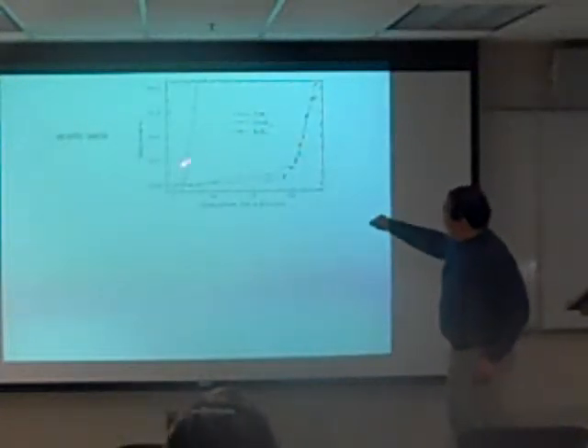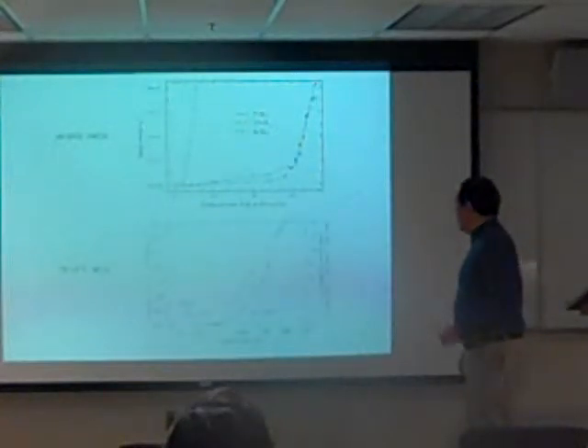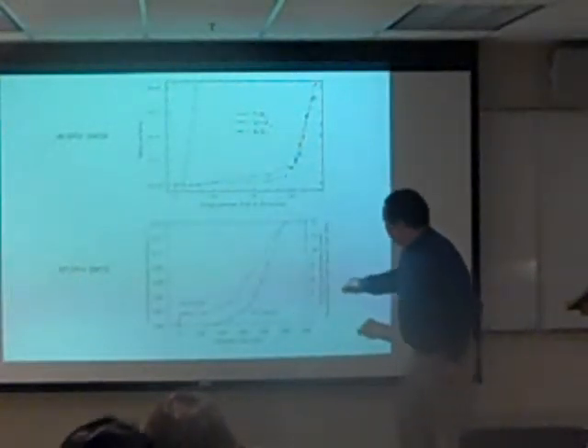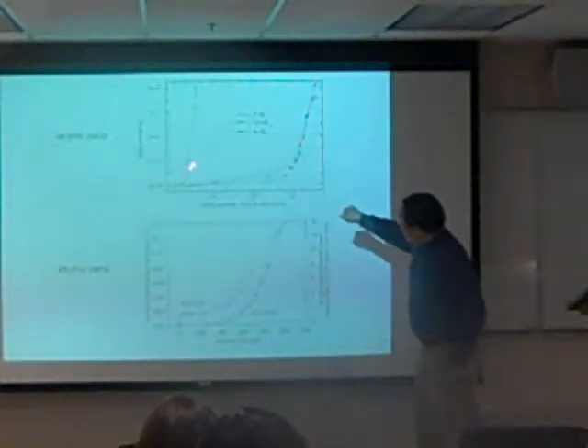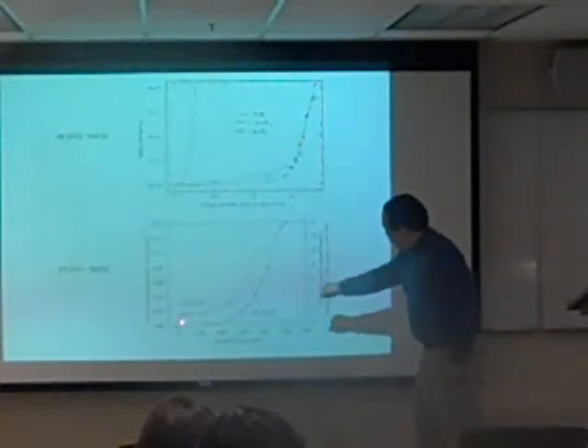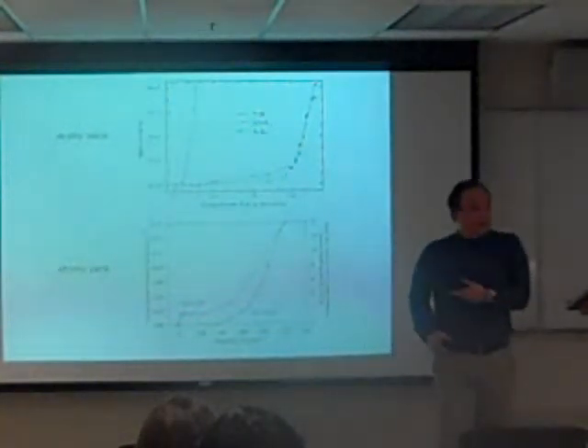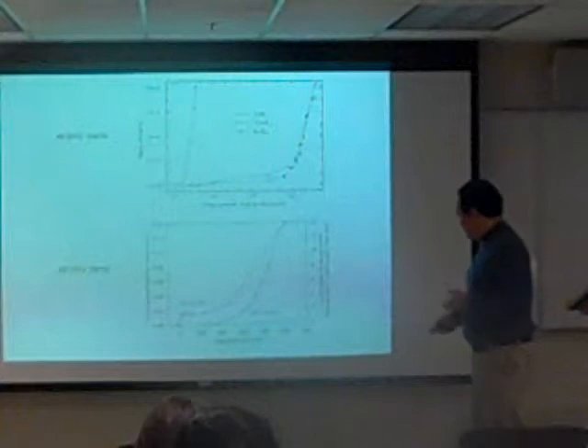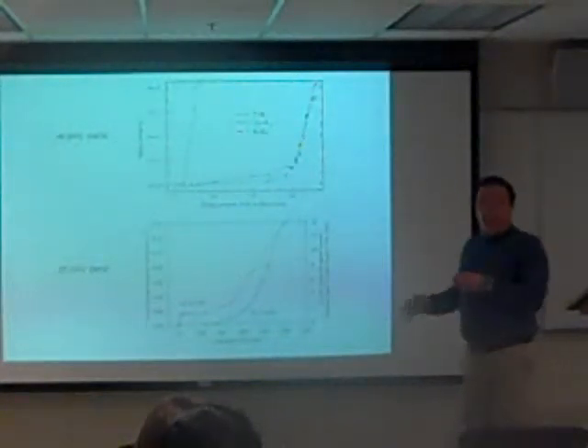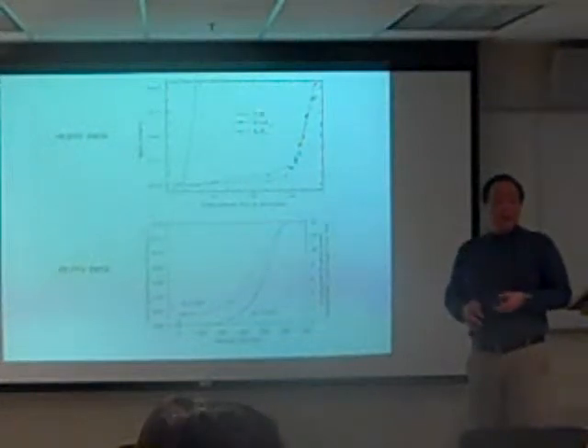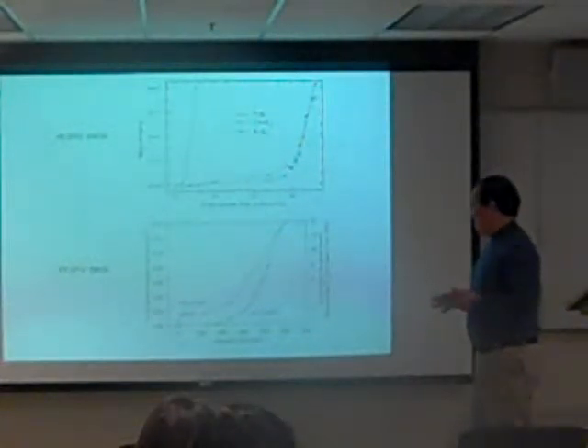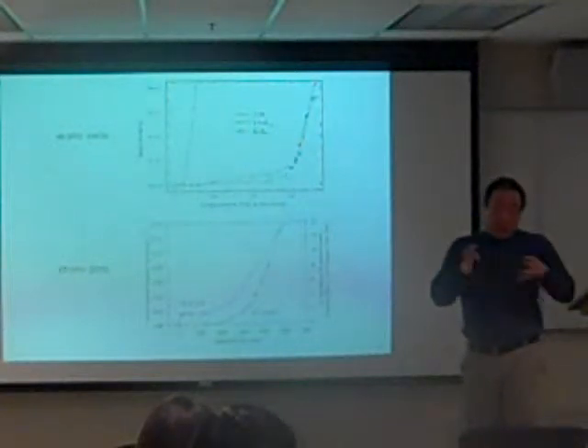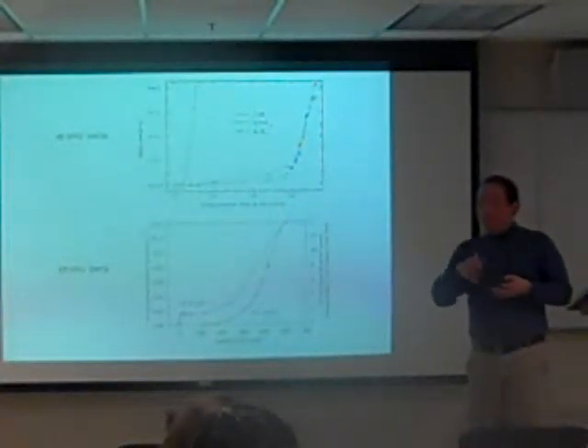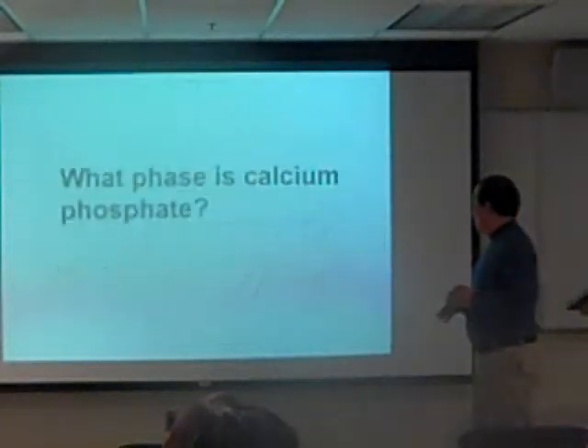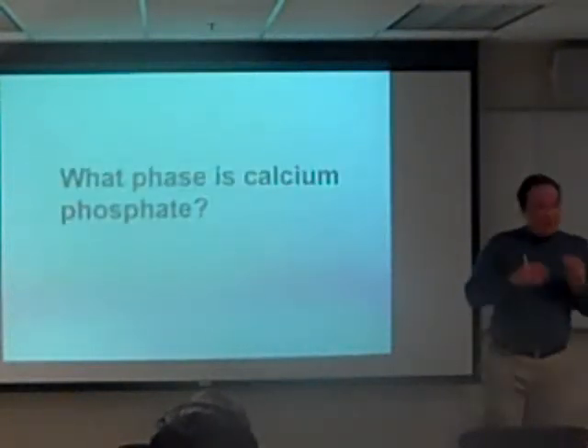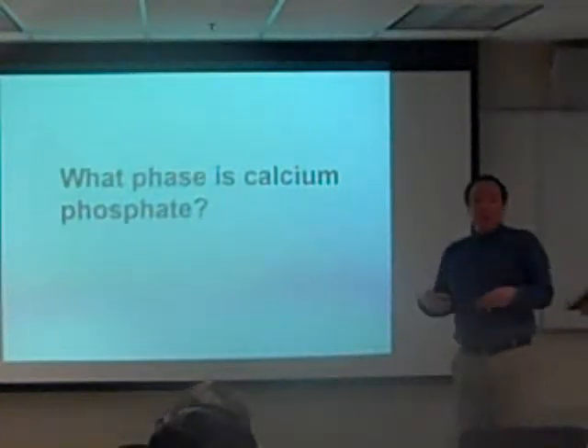So this is the in situ data that we saw from the constant composition apparatus. If we go down here, this is using the ultra-high vacuum data. This data here is replotted right here, and this data here is taken from a series of mass spec experiments. You can see that there is a correlation between at least the kinetic growth of phosphate in both the ex situ and in situ data. Now, of course, the caveat is, yes, you are interrupting equilibrium, but it looks like roughly, you can match the behavior.